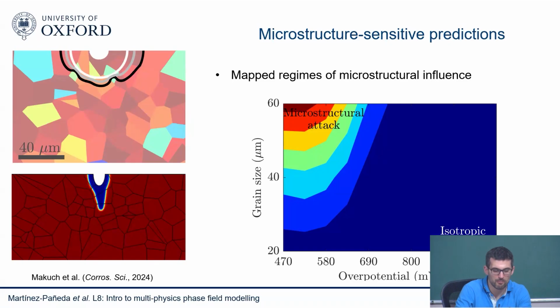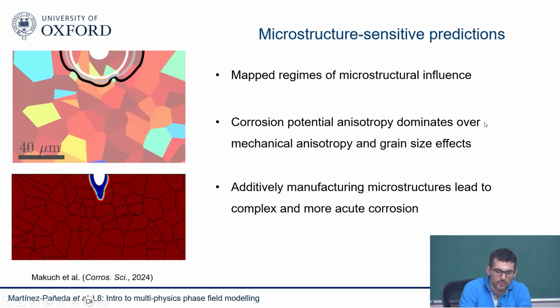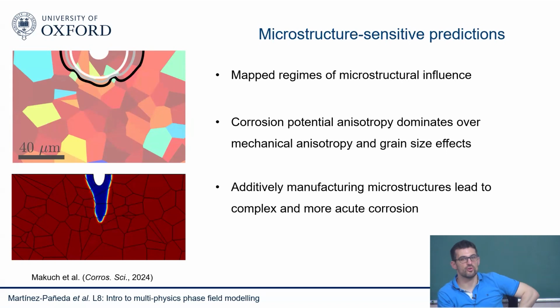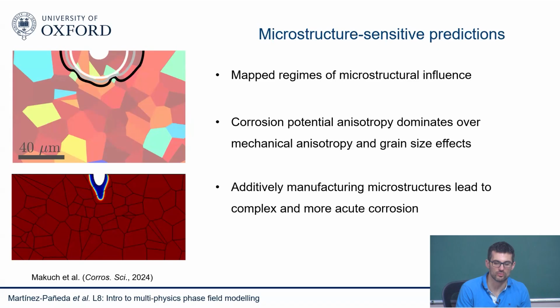We tried to build maps that look like this one, where you basically understand in which cases you have some sort of microstructural dependence, and in which cases you can get away with a simpler model. This was the idea. And then other things that we learned was that the corrosion potential anisotropy dominates over mechanical anisotropy and grain size effects. And we also use this to understand, and this is also a group in the US, in Notre Dame, we're trying to understand what is the effect of additive manufacturing, metal 3D printing, right? So how can additive manufacturing microstructures lead to more complex and more acute corrosion? So we know that the microstructures are going to be very different. We know that there's a little bit more susceptibility to corrosion, so we can input those microstructures and understand why they are a bit more susceptible to corrosion.